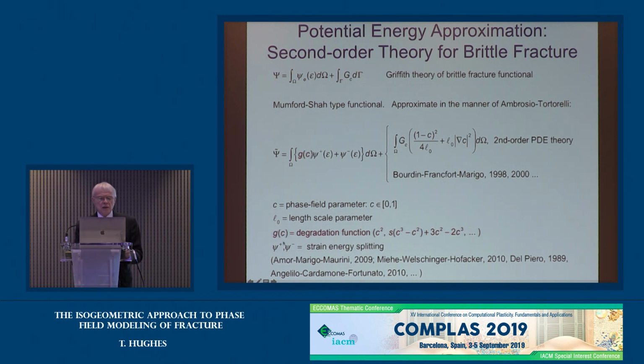The damage is either all or part of the strain energy, in this case, the elastic energy. Now, that has been done in various ways. There are various splits. I won't go into them. I'll just mention that they're all typically trying to fracture only areas where tension is taking place. Fractures usually occur in tension and not compression. So you're making some kind of a compressive-tensile split. And there have been various ways of doing this that are close to that theme, but maybe don't take it all the way. But recently it's been discovered in the masonry literature that this problem is basically a solved problem, at least for linear elastic materials. And you can do the splitting such that you really just damage tension and not compression.